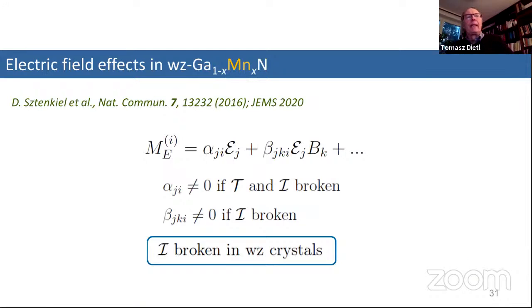Okay, so this was kind of where we are now, but now we turn to the second part of the talk, concerning electric field effects in this gallium manganese nitride. We are now prepared, we know a lot about the system to understand the physics of electric field effects in the system. What we know from the general theory of magnetoelectric effects is that to observe it without an external magnetic field, you have to have broken time reversal symmetry and inversion symmetry. And if time reversal symmetry is not broken, you need a magnetic field to break it.